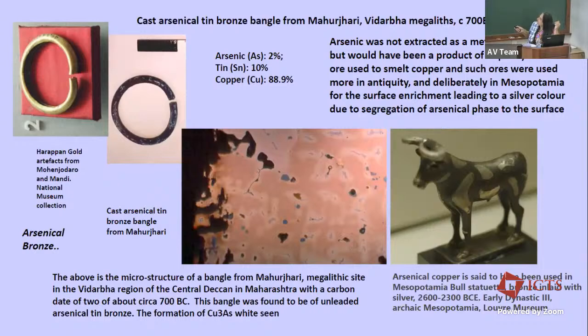And this was actually known by the Mesopotamians, and some of these arsenical bulls, you can see some of the silvery surface, which is due to the arsenic segregation. And we think they were deliberately using arsenical bronze for this purpose. But what is interesting also was that you do find some examples of arsenical copper also in the Harappan repertoire, and then it seems to carry on into the peninsular region also.